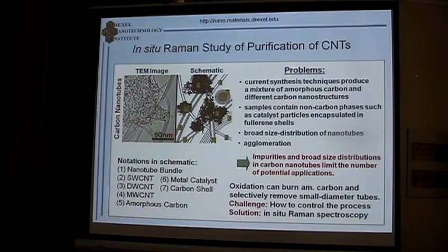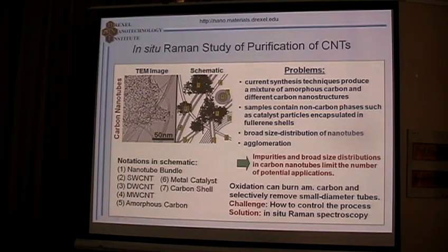All samples of nanotubes produced usually have plenty of amorphous carbon along with carbon nanotubes. In industry, it's mainly purified by acid oxidation, which is a nasty process, not environmentally friendly, slow, bad. And it was believed for a long time that oxidation in air, while cleaner, always burns nanotubes. It's impossible to find conditions here.